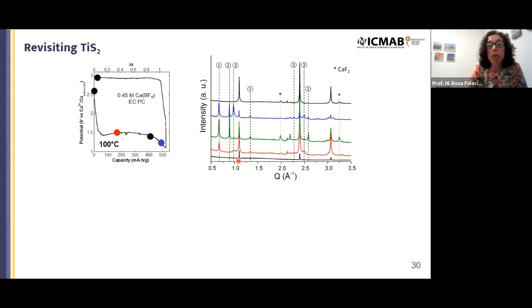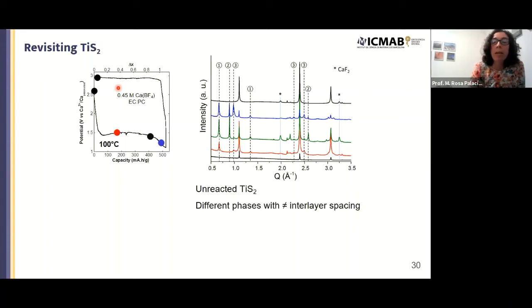This is the X-ray diffraction pattern. So from the very beginning, we see peaks at low angles. There seems to be more than one phase formed, so probably there is a kinetic issue. But then when we reverse the current, we are able to oxidize and to recover TiS2 again. So the process seems to be reversible, despite the large polarization, so far from being commercially interesting for the moment. The fact that there is also some unreacted TiS2 means that there is also an issue with kinetics.